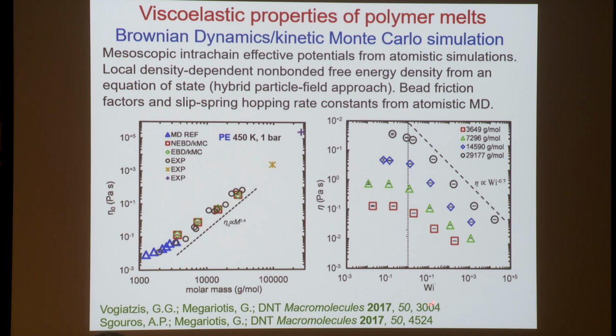One can also try to calculate the viscosity itself as a function of the shear rate. And here, instead of the shear rate, we use the Weissenberg number, which is the shear rate times the longest relaxation time of the melt. And for various molecular weights, we see this prediction for the eta as a function of the Weissenberg number. We see that for low Weissenberg numbers, the eta plateaus to a value that we call eta 0. We have the Newtonian plateau. But for large Weissenberg numbers, for strong flows, we see that there is a pronounced shear thinning behavior in these melts. That is well known. And the exponent that expresses this dependence on the shear rate or on the Weissenberg number is minus 0.7, close to what is measured experimentally.